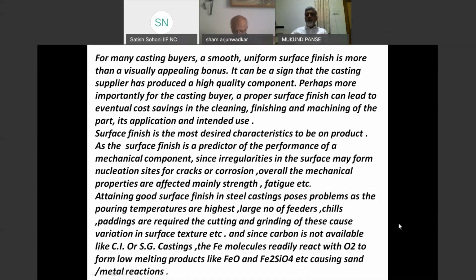Also, the typical phenomenon of reaction with the mold is caused by the oxidation of the iron particles, which does not happen in CI or SG casting as the carbon itself is very high, and also the carbon in the sand and paint helps, and that's why you get a better finish in SG and CI casting compared to steel castings.